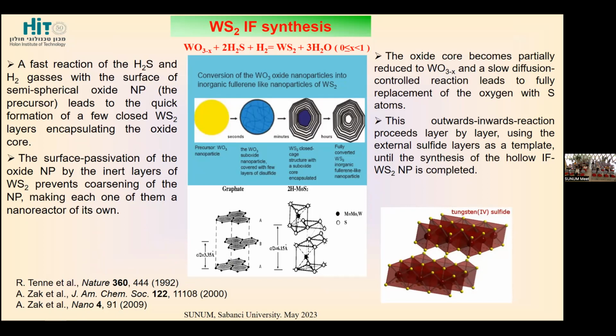This is a multi-step process where we start from the oxide, and through oxidation-reduction reactions, both fast and slow, we come from the outside to the inside, converting this oxide to WS2. We always start from outside to inside until we get this fully covered WS2 inorganic structure. We call this a fullerene-like nanoparticle.